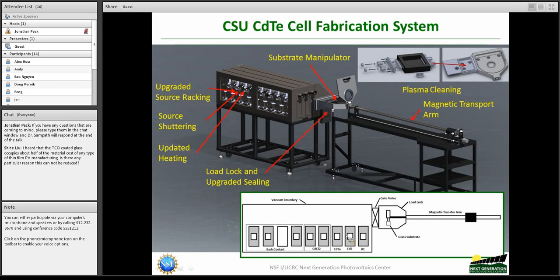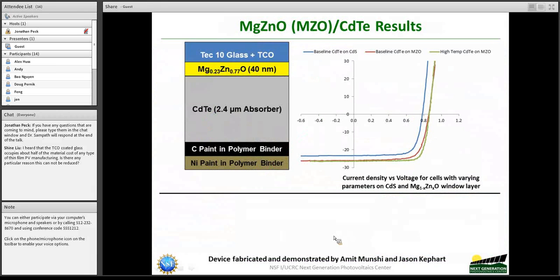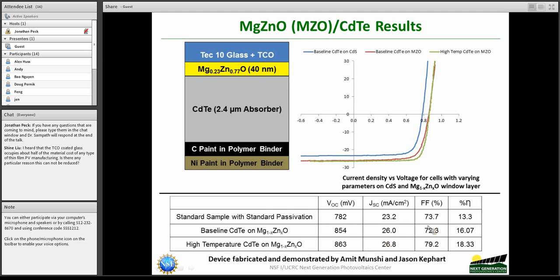So we have explored a large number of process conditions and processing strategies to improve the cadmium telluride device. For the first year, the magnesium zinc oxide result that is shown here is still done on the Tec 10 glass with the TCO. And when we put this material, magnesium zinc oxide, with this cadmium telluride absorber, you see some significant improvement in the performance. The blue curve is what it was with just plain cadmium sulfide. The orange is with magnesium zinc oxide, followed by cadmium telluride. And here are the efficiency numbers. So we have gone from 13.3% with the cadmium sulfide window layer to now verified and certified 18.33% with the magnesium zinc oxide layer here.